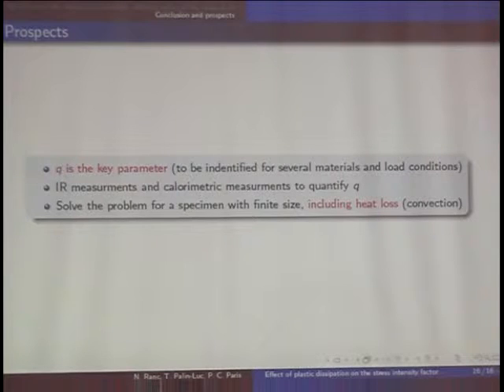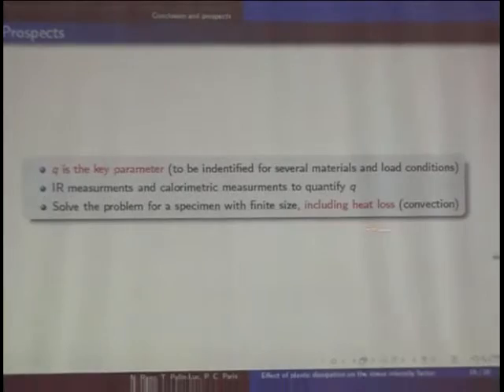So you can assess approximately what is the effect, but it's very dependent on the size of the specimen, because it's very dependent on the thermal boundary conditions. And we also have to solve the problem in the case of a finite size, including all the heat loss, which are very important. But I think that considering the thermal effect on K is important if we want, for instance, to revisit many experimental data, for instance, about the frequency effect, maybe about what happens in air and what happens in vacuum, because when you are in vacuum there is no convection loss, and maybe other interesting things like that. Thank you for your attention.